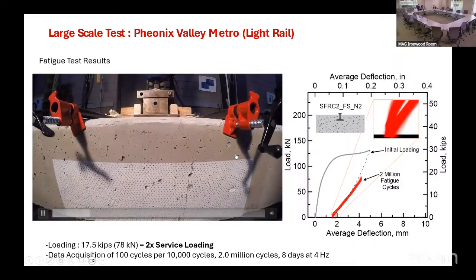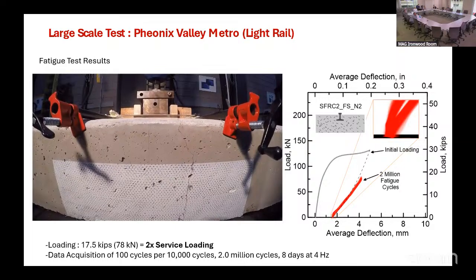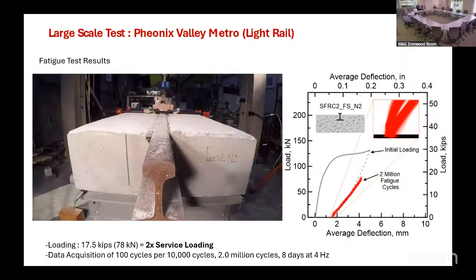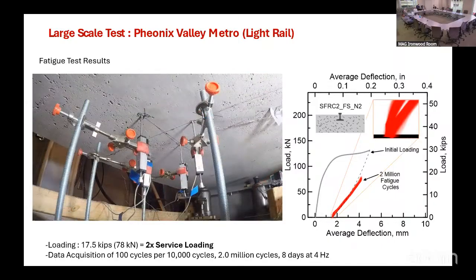So there is a sound that you can see. So this is the level of deformation. After first you crack it, so we apply the load, crack it, and then you go through 8 days of basically this type of test. At the end, you unload it. So what you see is that, by the end, you still have a lot of stiffness in the section.